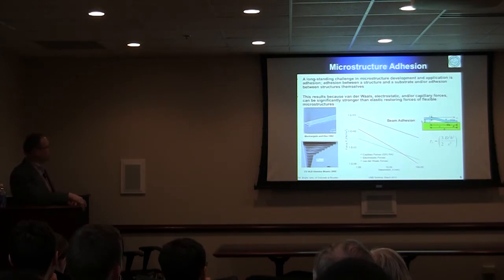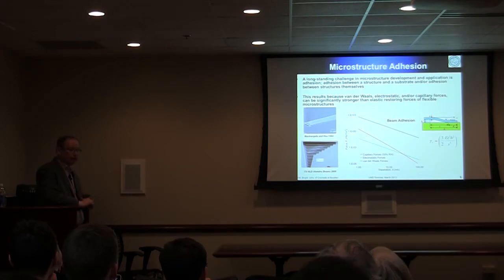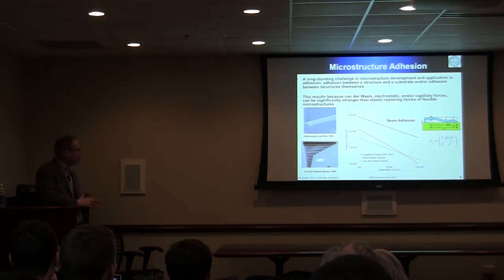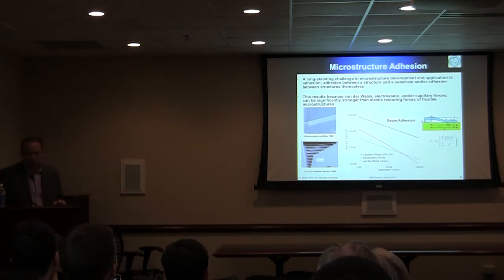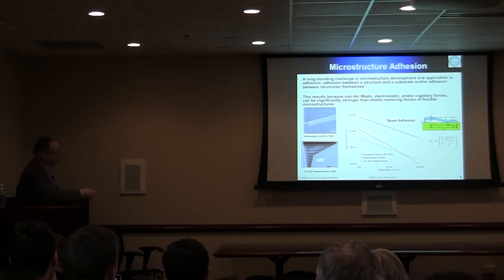So first, the microstructure adhesion. We've been looking at this problem for a long, long time. In fact, the very first work we introduced to the MEMS community on ALD was for this application, adhesion control. Adhesion happens due to a combination of three forces: capillary, electrostatic, and van der Waals forces. And you can design ALD-type coatings to control pretty much any of those or a combination. What you see here is a traditional way of looking at beam adhesion. This is a polysilicon suspended beam.